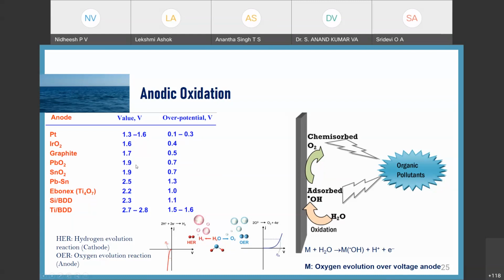Then coming to the oxidation potential of these electrodes: platinum, about 1.3, 0.7, iridium oxide, graphite, lead oxide, tin oxide, lead-tin combination, Ebonex, which is a commercial name, and the silicon or titanium boron-doped diamond, BDD. All these electrode materials have higher oxidation potential. So that potential we make use of for generating hydroxyl radicals.